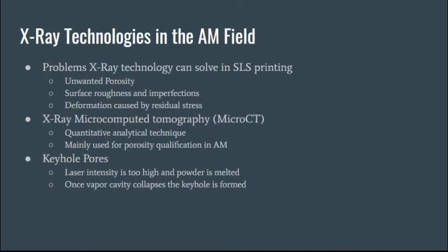Some issues that X-ray technologies can help to solve in the additive manufacturing field are unwanted porosity, surface roughness and imperfections, and deformation caused by residual stress. Porosity is just how it sounds. The surface finish of the products can have a varied appearance and a varied feel, and this is not good for taking these products to market or using them as prototypes. We want the model that engineers are using to be exactly preserved when it comes out of the 3D printer, but if the printer is introducing this porosity, it's unwelcome. That goes along with surface roughness and imperfections too.